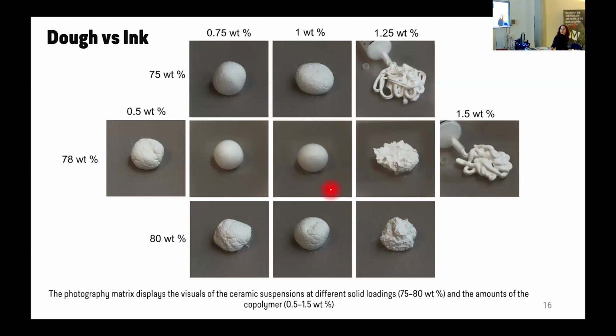So if you look at this, with the same type of polymer, right? You could get different particle loadings. And if you look here, 78 weight% ceramic and 1 weight% additive, you get a very nice dough. But then if you start increasing the amount of the additive in the system, you end up having an ink, because that polymer is behaving like a dispersant as well. So if you put so much in it, you are going to have a system that flows. And if you would like to do the dough, you don't want the system to flow. So we stop here, right?